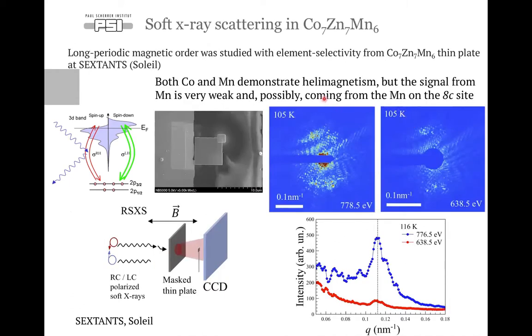We have also performed a transmission type soft X-ray scattering experiment on the same material. For this, we prepared a thin lamella with a thickness of 200 nanometers of cobalt zinc manganese 776 and measured the resonant small angle X-ray scattering at both the cobalt L-edge and the manganese L-edge. And again, we have seen that the magnitude of the scattering signal at the manganese side is much, much weaker than the one at the cobalt side. From this, we can conclude that the helimagnetism, or main ferromagnetic moment, is coming from cobalt only, while manganese has a frustrated lattice and has the dominant antiferromagnetic coupling, and basically it doesn't participate in the helimagnetic structure, but only contributes to these short-range correlations that we observed in the neutron scattering experiment.